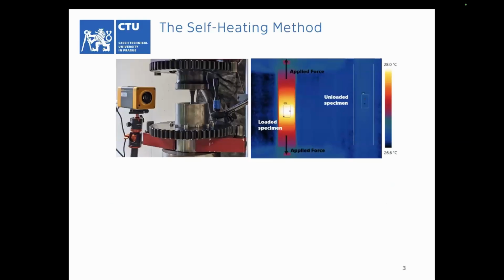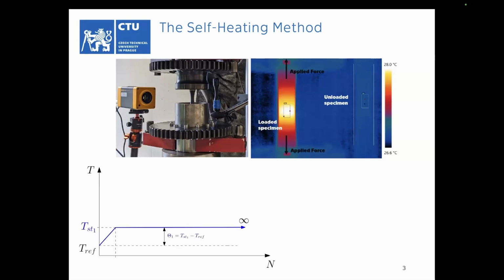The method takes advantage of thermomechanical coupling. If you cycle the specimen, some portion of mechanical energy dissipates to heat due to internal friction or microplasticity, and it's emitted outside and can therefore be detected by infrared cameras. The progress of temperature when you cycle the specimen is schematically shown here. In the beginning, you can see a quite steep increase, followed by a stabilized phase. If you cycle the specimen above the fatigue limit, you can also observe a third stage, which is attributed to the presence of a crack and plastic zone at the crack front.